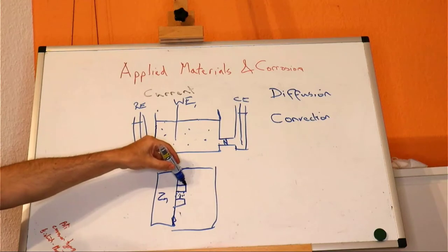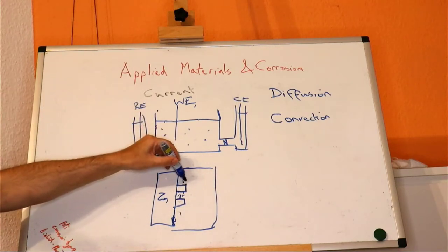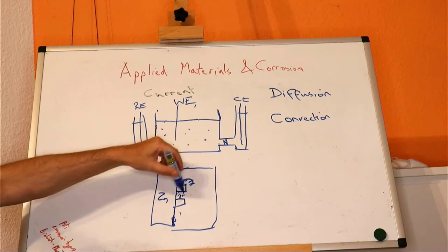Obviously, this corner here, which is now exposed to the solution, is better because the zinc ions created can diffuse out in all these directions, whereas in here they can't because there's another wall, and so it's also generating zinc ions. So if we increase the viscosity, we can naturally promote our zinc to etch flatter. It will etch polish itself.